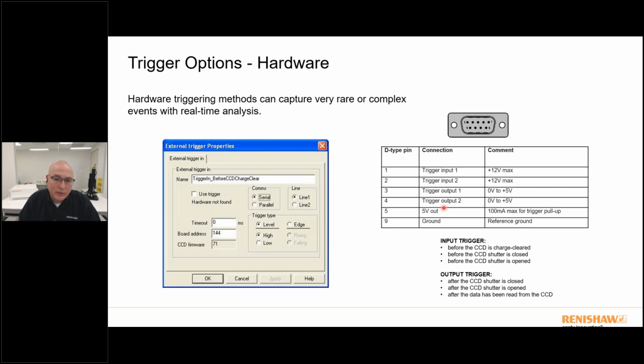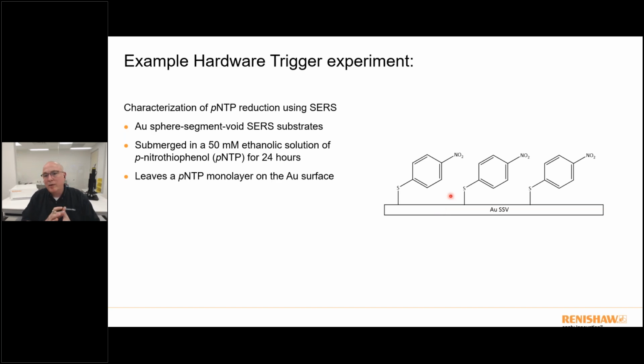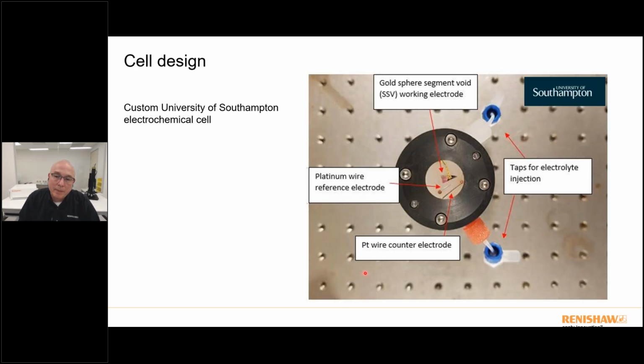So I'm just going to briefly describe an experiment where this was used successfully recently. And this is really looking at the para-nitrothiophenol. This is a sphere segmented void gold SERS substrate where that substrate had been submerged in a 50 millimolar solution of that NTP. And that allowed a monolayer of the NTP to exist. Now, all this work was done at University of Southampton.